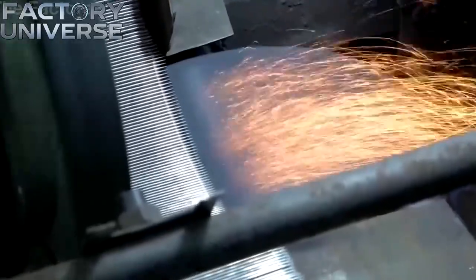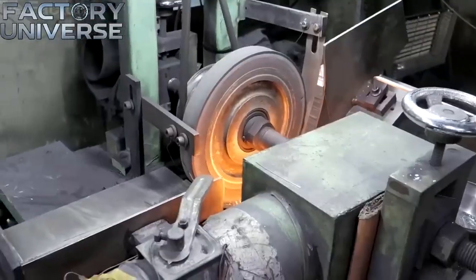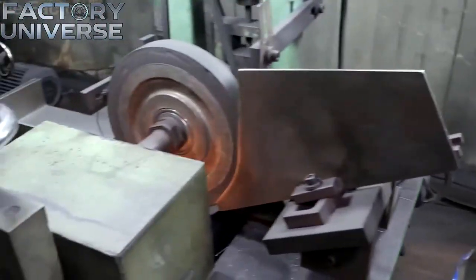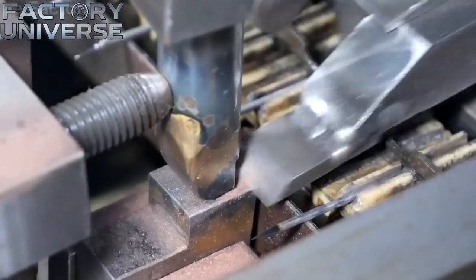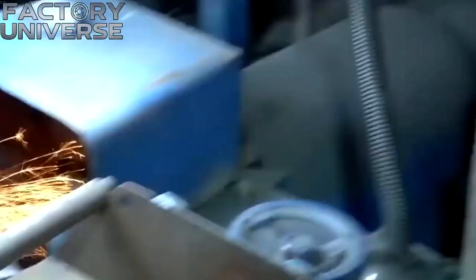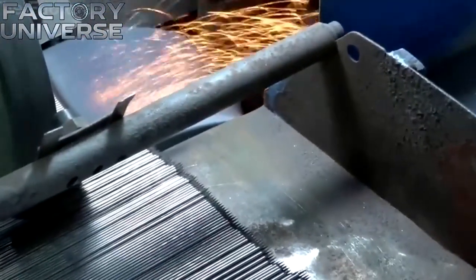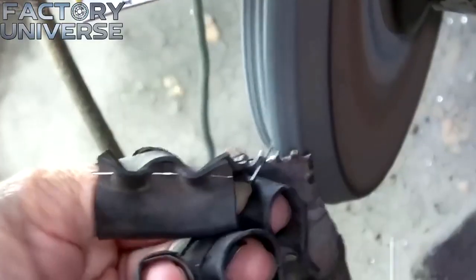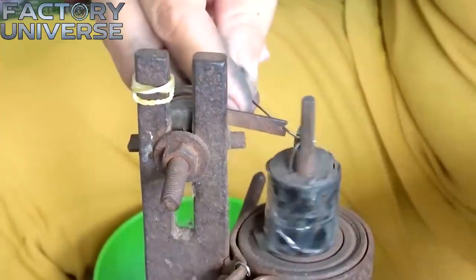Tiny sparks scatter at every millisecond of contact, acting as a visible indicator of the intense friction separating material from the core. At the same time, automated systems must monitor the pressure and the exact duration of contact to prevent the steel from overheating. It looks superficially simple to sharpen a wire, but in reality, thermal deviation can ruin the structural integrity of the metal.